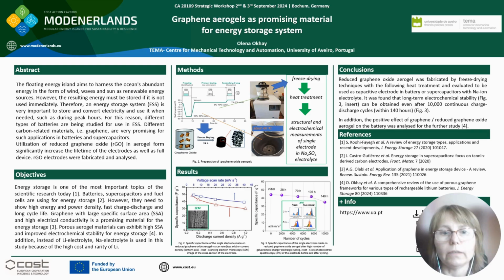In addition, lithium is a very expensive and rare material, and as you know, lithium is used in commercial batteries for energy storage. We decided to use a sodium ion electrolyte and study our graphene oxide aerogel-based electrode to test it. As you can see in figure 2 and figure 3, those electrodes were very stable chemically and mechanically, and almost unchanged after a high number of charge-discharge cycles. You can see that after more than 100 hours of continuous work, they are stable. We think to continue this work to modify reduced graphene oxide with other metal ions and study it. Thank you very much for your attention.